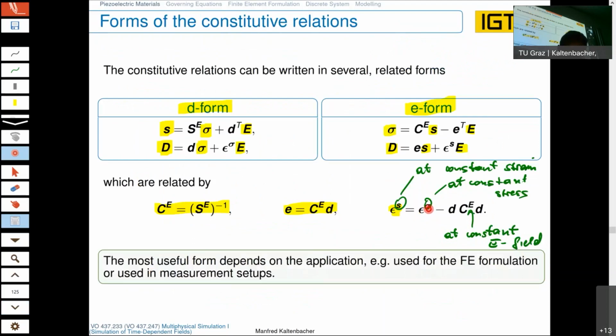And the easiest way clearly is to have the sample free hanging so that the stress is more or less 0. Constant stress also is 0 stress. Yeah? It's not necessary to have 0 stress, but constant stress, and the easiest way is to have a setup like hanging the sample, and then you get this 0 stress.